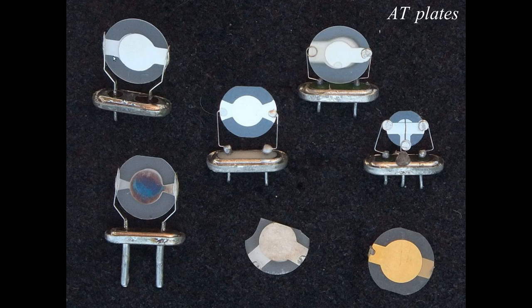Besides single resonators, we may have double resonators and coupled double resonators. So this sample here is a monolithic crystal filter with two mechanically coupled resonators, and they have one common electrode here, and each section has its own excitation electrode. For instance, the signal enters here, first makes the first resonator oscillate, then the first resonator is mechanically coupled to the second resonator, and the second resonator is piezoelectrically coupled to the electrode outside here. So this has a three-point attachment. This one has only two attachment points. This has a three-point attachment because we need three electrical connections for such a signal.